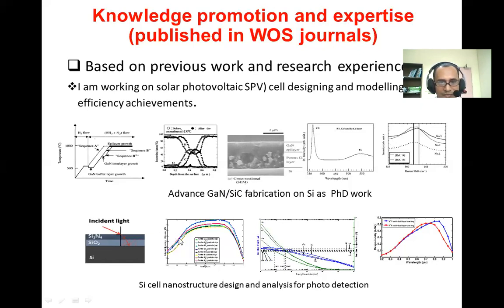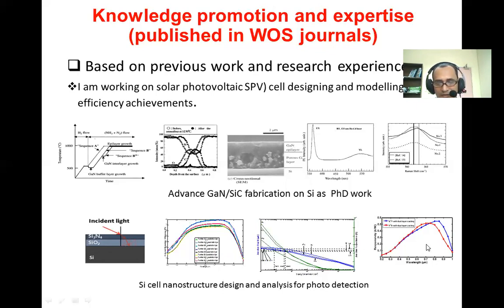In the modeling of gallium-silicon solar photovoltaics, using traditional silicon oxide and silicon nitride interfaces as passivation layers, you can see the different responsivity behavior from different interlayer depositions at the interface. Silicon dioxide and different doping concentrations produced different levels of responsivity. For n-type and p-type silicon photovoltaic applications, you can see the responsivity variation for blue and red wavelengths — it varies definitely.